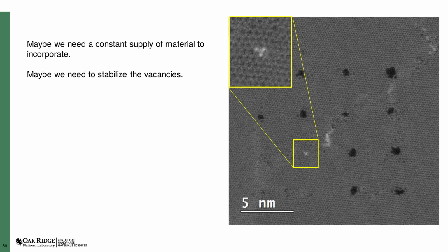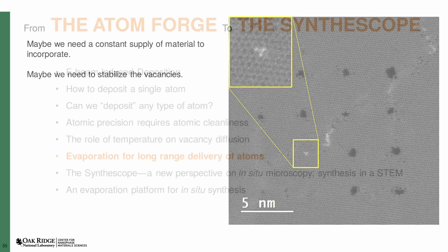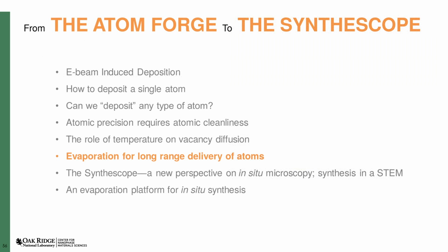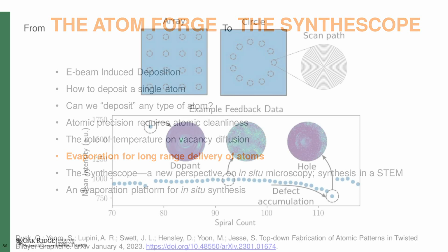Maybe we can attach impurities to the vacancies the moment they are formed. And if we can somehow stabilize the vacancies, this may give us a little more time for the impurity atom to attach. What we would like to do, then, is to somehow deliver atomized material to the region of interest. Since we are already, at this point, operating on a heater chip, maybe if we just put our desired source material on the graphene surface, some of the atoms will be thermally freed from the parent nanoparticles and diffused to where we want them.